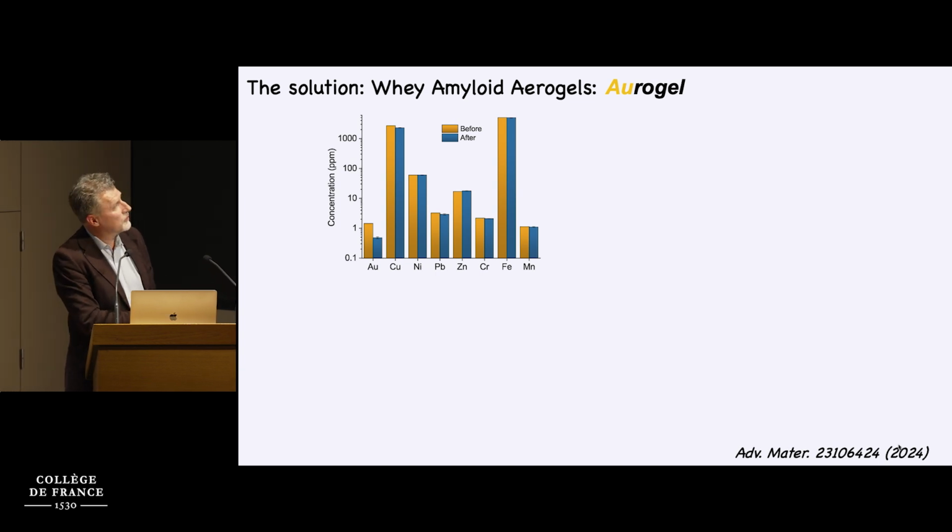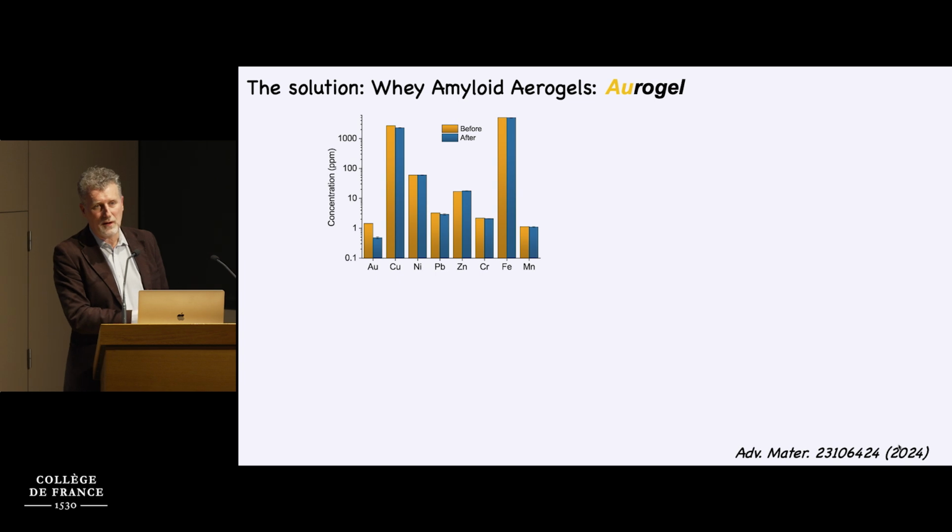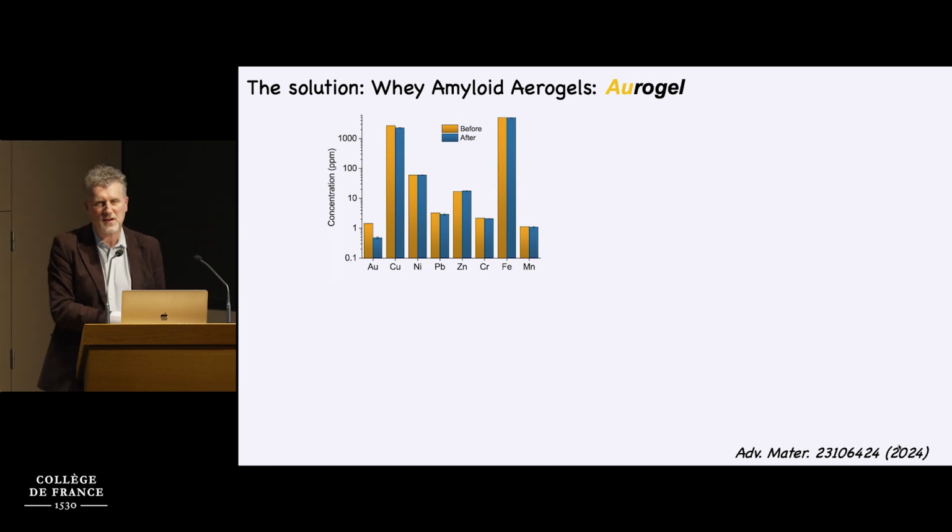This is what you dissolve, what you have in the e-waste dissolve before and after extraction. You see, yes, there is 1 part per million of gold, but look how much copper, look how much iron. So when the postdoc came to me and said, let's try to see what we can extract, I said, you will have mostly copper and iron.